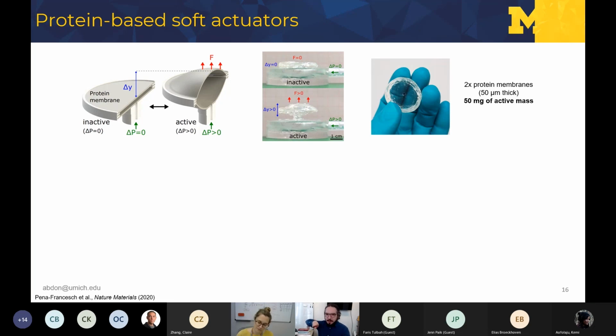heat, so we can kickstart and really speed up the healing process by creating as many beta sheets as we can. So that increases the Young's modulus a little bit. But if you just let it heal on its own over a longer period of time, minutes rather than seconds, then you shouldn't have this problem. In any case, we didn't see much change in the performance, because you start seeing that big difference in modulus when you are stretching at large strain. Keep in mind that here you are pressurizing and bending, not really stretching the membrane, so it's not that critical. But that's a very good point.